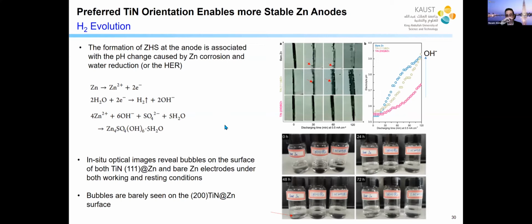So how does this phase actually form? Basically, here's what we believe is happening. The zinc goes through this reaction during the dissolution process, forming these two electrons. In the water, these two electrons are picked up and then form this hydroxyl. This hydroxyl can react with the zinc and the sulfate, and it can form this phase. This, of course, leads to hydrogen.